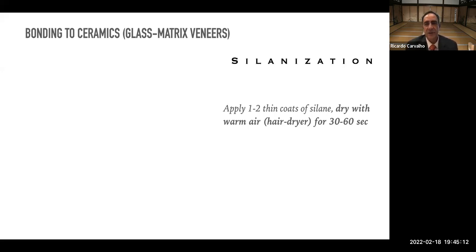And silanization from the clinical perspective is really a simple procedure, and we should pay attention because although it is simple, it can be quite damaging to the bond if we apply it incorrectly. So ideally, silane should be applied in a very thin coat, 1 or 2 coats of silane. And after you apply the silane, we recommend to dry with warm air for 30 to 60 seconds. And you will see this.